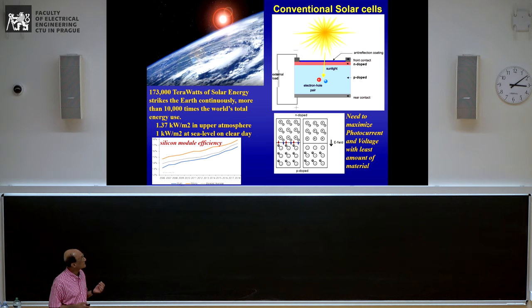There are opportunities for absorbing an enormous amount of sunlight in a much thinner region than has been traditionally believed. Silicon module efficiencies have been growing steadily, and at this time are roughly between 17 and 19 percent, still increasing slowly. But these are made of relatively thick silicon materials, and with thinner silicon it's actually possible to absorb as much or more light and at the same time reduce recombination effects.